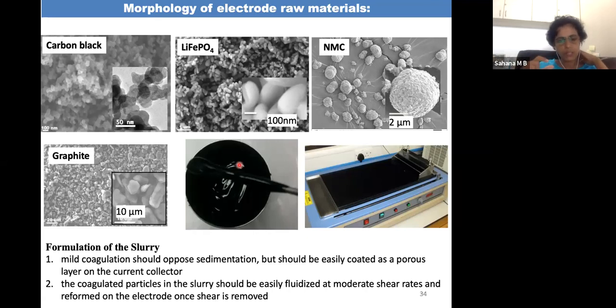So we need a mild coagulation of the particles in the slurry, so that it doesn't sediment. But the coagulation should not be too much. If the coagulation is too much, we will not be in a position to coat it. Once we put this slurry on the current collector, we apply some shear force and spread it over that. So the coagulation should be mild, such that when we remove the force after the coating, it comes back. The active materials should bind together again.